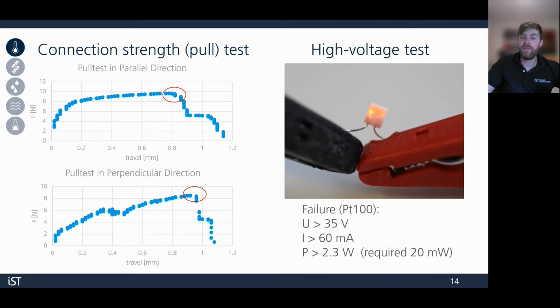On the right side, we have a high voltage test. Pictured here, we have the 100 ohm element. You can see we're really heating it up and it's glowing bright. We're trying to push it to failure. This sensor was able to withstand over 35 volts, over 60 milliamps, and over 2.3 watts. We note here that according to the detail spec, the sensor is only required to withstand 20 milliwatts. With our tests, we were actually unable to destroy the 1000 ohm variant.